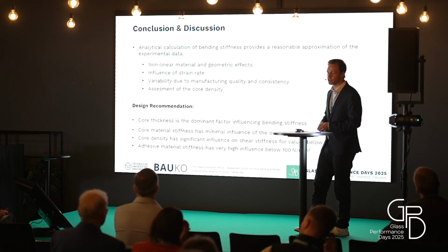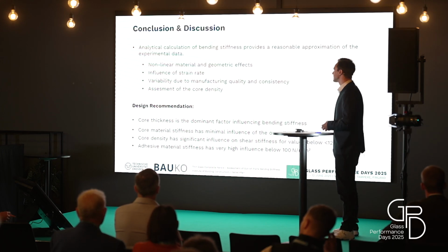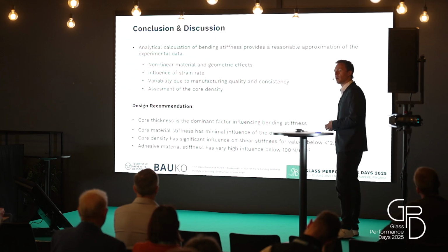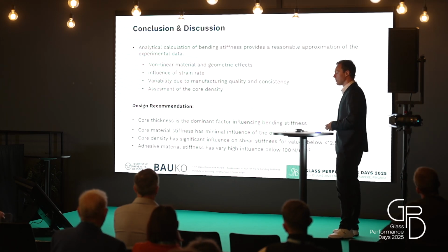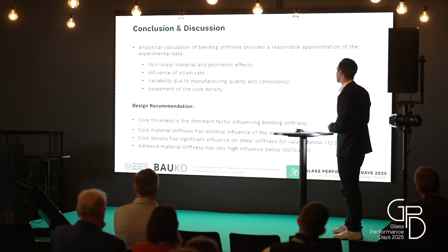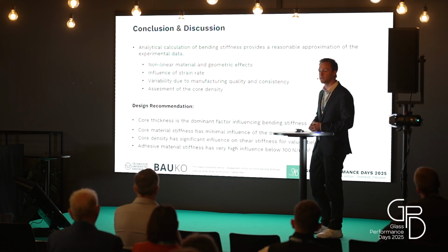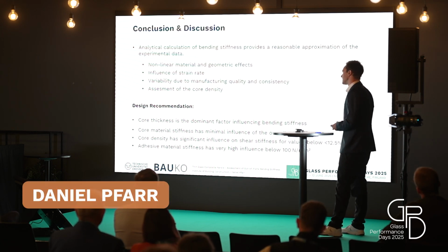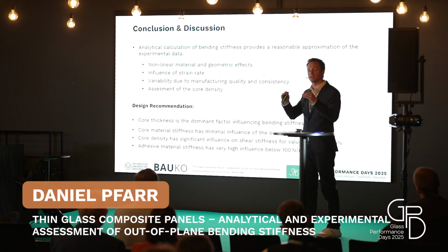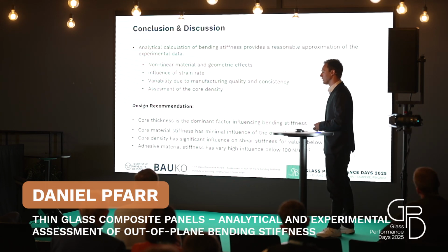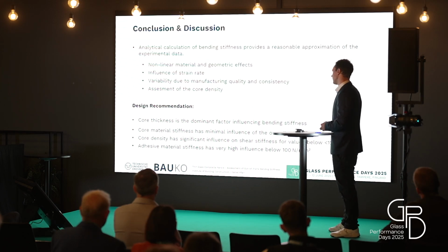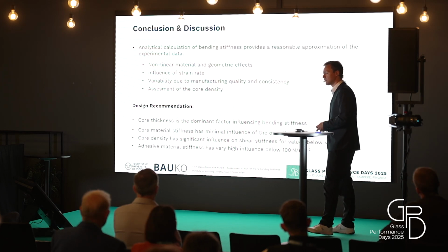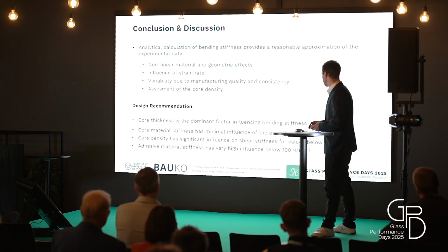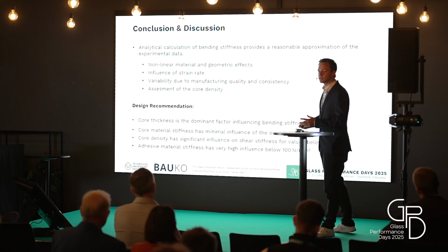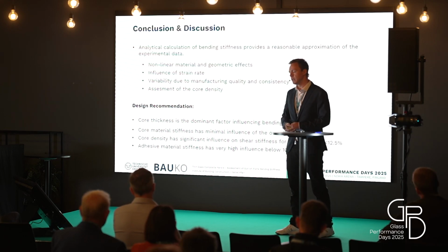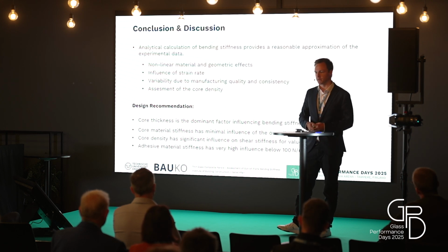And we have some design recommendations at the very end coming from our parameter study. We can say that the core thickness is the dominant factor when we want to influence the bending stiffness of the composite. The core material stiffness has more or less a very minimal influence on the overall stiffness, which gives us a little bit of freedom in the choice of our material for the core. And the core density has a significant influence, but as long as we achieve a certain amount of core density, we can hold this threshold and limit the total deformation. And last but not least, the adhesive material, of course, is a very significant component. So at least we need to hold maybe 100 Newton per square millimeter, at least for this setup we have investigated, to ensure a certain stiffness, especially shear stiffness, for the composite.